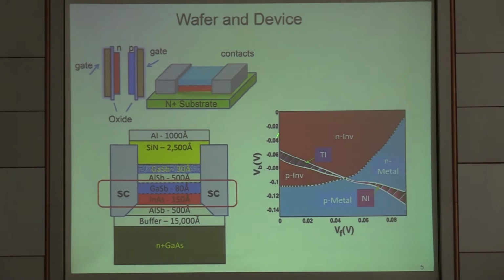This phase diagram really is plotted in terms of the front gate voltage and the back gate voltage. So you can turn this system into a charge neutral point. Here is a line. Along this line, basically, the electron density will be equal to the hole density. Therefore, the whole system is charge neutral. So along this charge neutral line, you have some range of the parameter where you can see the topological insulator.